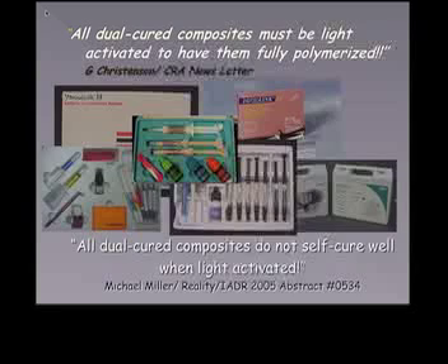It's very difficult to make stable dual cure chemistry, and that's what this slide shows. A dual cure composite must be light activated to have them fully polymerized. That's Gordon Christensen from the CRA newsletter. All dual cure composites do not self-cure well when light activated.